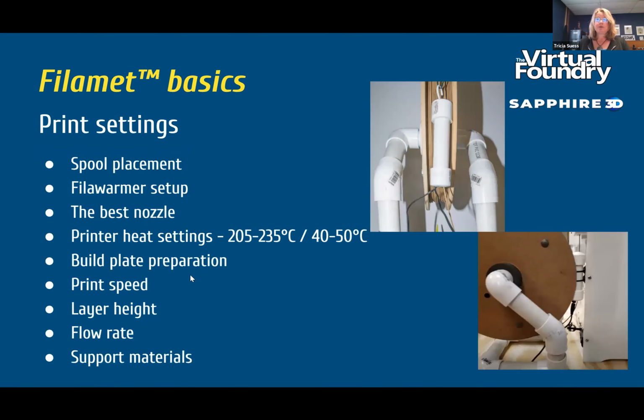Now we'll walk through the print settings here, and Brad, I'll hand the mic over to you again to talk us through each of these items. Okay. So the Filawarmer is a very simple device. It sits at the edge of the spool. As the filament comes off the spool, the Filawarmer warms it. Specifically, it takes it to about 65 Celsius and oscillates between plus and minus 10 degrees Celsius in that range. That does a couple things. Most importantly, it takes the memory out of the plastic that it gained while it was on the spool. Otherwise, the material would continue to want to be in that circular shape. So the Filawarmer relaxes that and straightens it out.